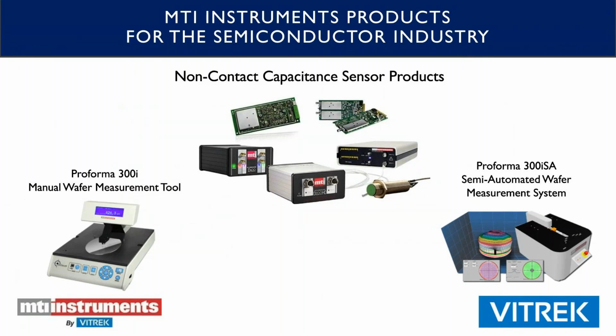Today we're going to focus on our two turnkey solutions. First, our manual gauge is the Proforma 300i on the left here, and our Proforma 300iSA, which is our semi-automated wafer measurement system. These are used to characterize and test wafers that are in process for thickness variation, and our semi-automated system can actually map your entire wafer for thickness, warp, global and local flatness, along with bow measurements. Those are very useful when processing to do a check on your wafer to make sure that you're within all the tolerances needed for the next stage in microchip processing and manufacturing.